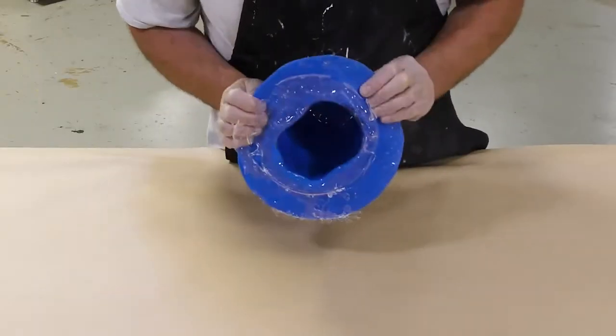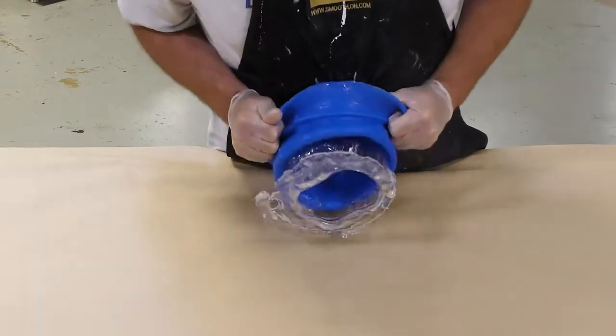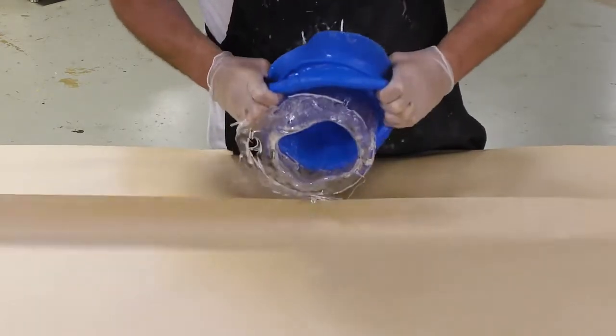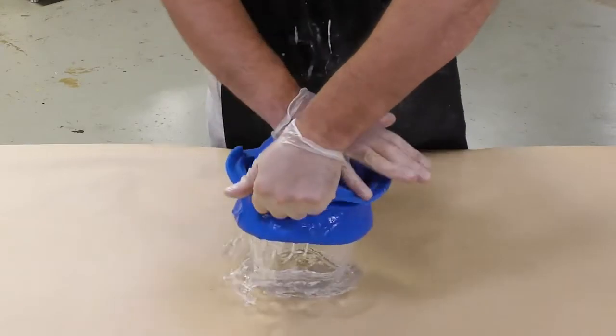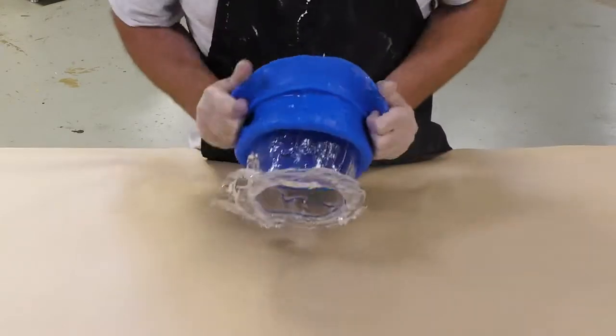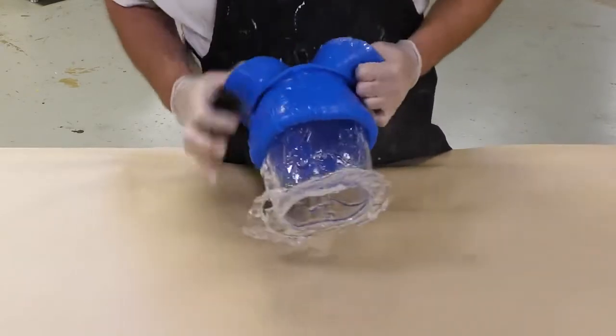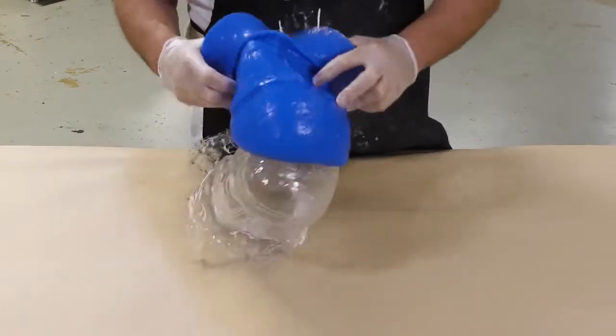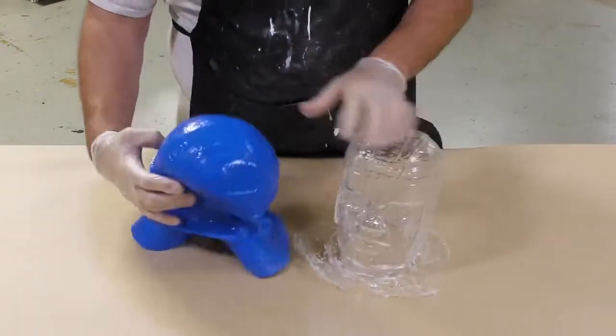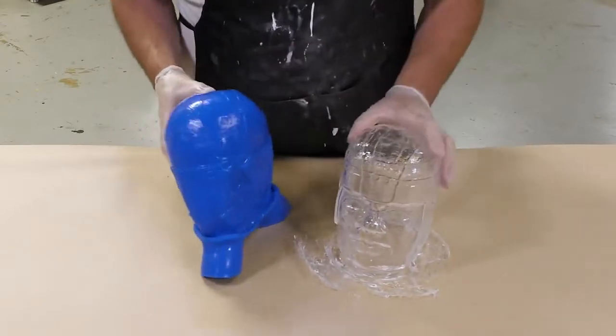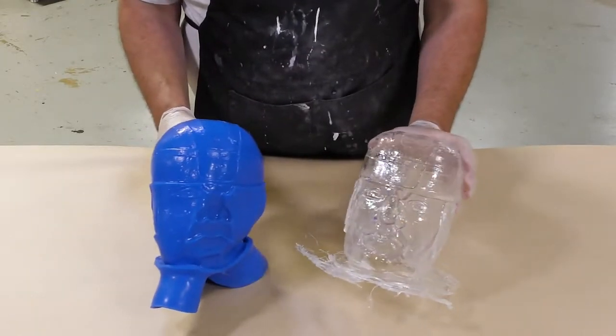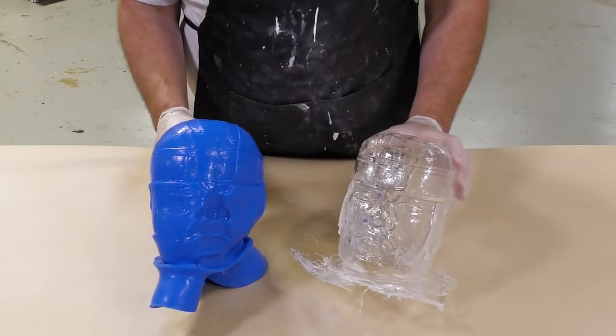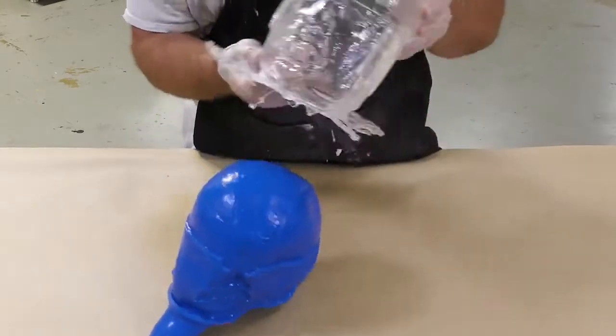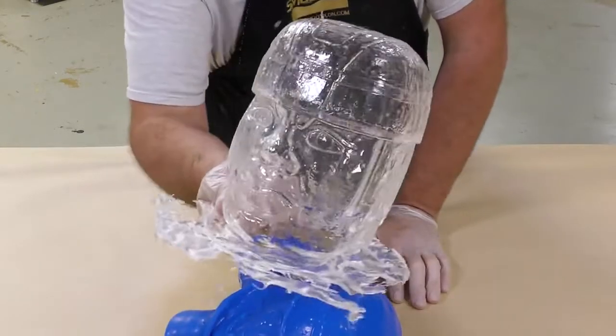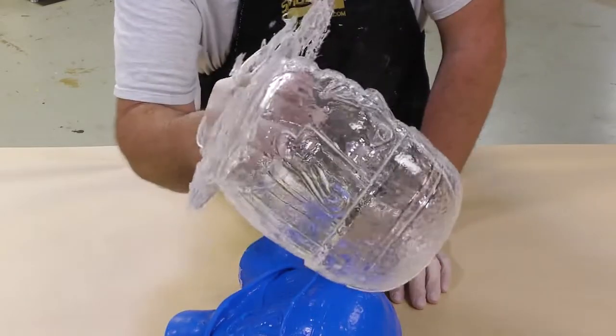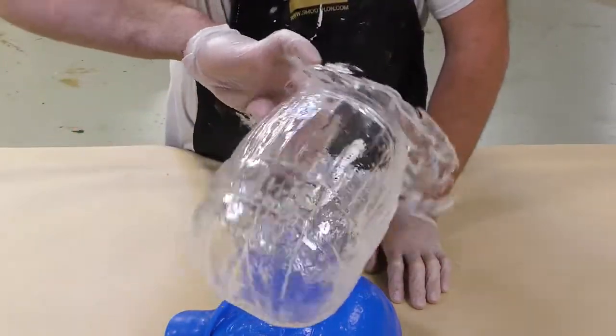After the cure, we can go ahead and demold our casting. And since this is a glove mold, this is a Moldstar 30 glove mold, we can simply peel the mold away to reveal our casting. The mold copied all the detail, including the glossy surface, onto our casting. The casting turned out successful, and I'm very happy the way that it actually turned out with minimal to no air bubble trap in the final casting.